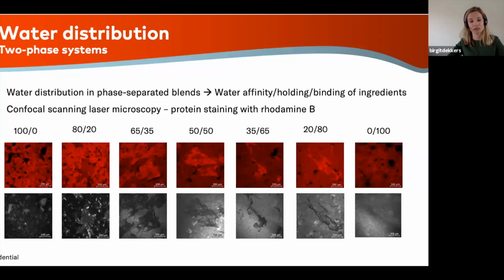And you see different types of affinities of the proteins for the rhodamine B, and also differences in light reflectance on the bottom side of this microscopy picture. What you can see, for example, in the 50-50 dispersion, where we mixed both proteins in equal amounts, is that the continuous matrix was one protein with the other protein dispersed. And you could see that the volume fraction of the dispersed protein was smaller than the continuous matrix.